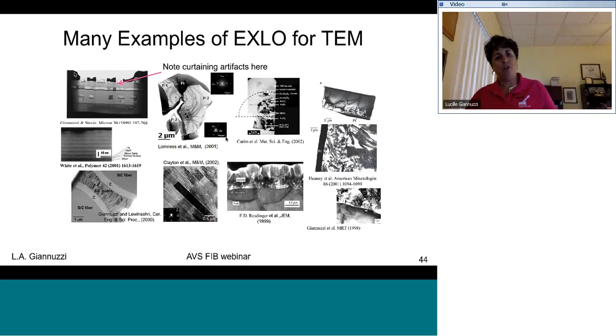So we didn't know at the time when we made all these samples, from semiconductors, from metal powder particles, to ceramics, to polymers, to geological materials. We were concerned with being able to FIB mill these samples. What we also learned is that these van der Waals forces actually work for all of this as well. Because of the reason I described earlier, because the Hamaker constant varies only a small amount relative to the van der Waals forces.